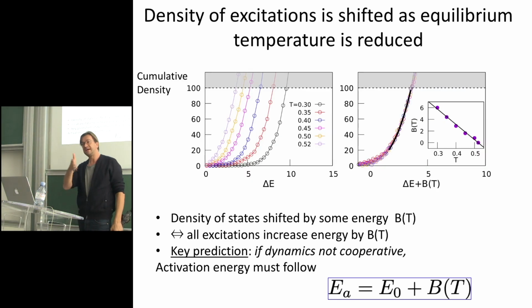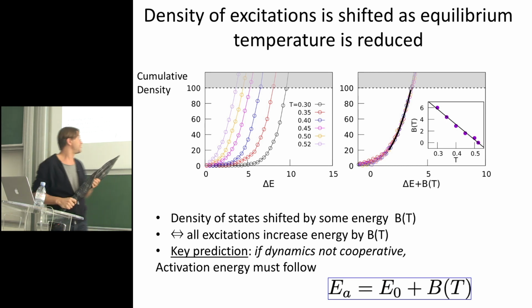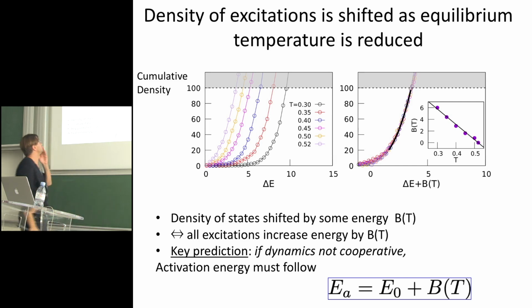Now we can study how this density of states, which is here shown only in the region where we believe it, evolves with temperature. Those different colors are different temperatures. This is actually rather large temperature, and this is very slow. We use the swap algorithm, a very strong algorithm, to equilibrate at very low temperatures. What you see is that as you quench a system, your density of excitations essentially creates a sort of gap. You don't find any excitation in a big range.